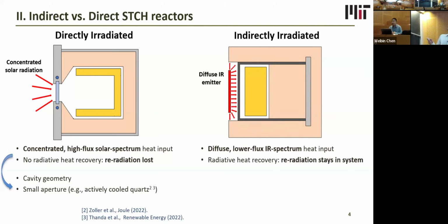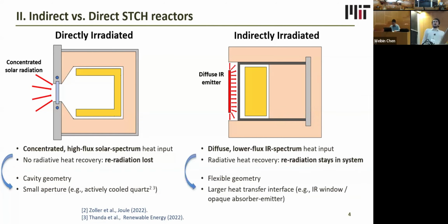On the other hand, this is what an indirectly irradiated reactor could look like. It uses diffuse lower flux infrared spectrum heat from a diffuse emitter, and it is designed for radiative heat recovery. So any re-radiation coming back off the reactor would stay in the system because it's reabsorbed into the emitter or an opposing reactor. Because of these differences, it has a more flexible geometry. It doesn't need to have this cavity geometry, and it will need a larger heat transfer interface because we're using less concentrated radiation. A larger interface is better for the speed of heat transfer.